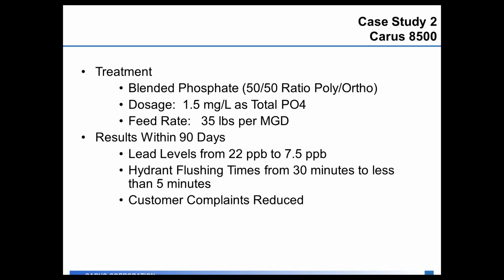Within 90 days of applying the blended phosphate to the distribution system, they had lead levels drop from 22 parts per billion down to 7.5 parts per billion. So now you're less than half of the action level of 15 parts per billion. Hydrant flushing times were reduced from 30 minutes to less than 5 minutes. So this reduced the amount of operator time in the distribution system to flush those pipes, plus the amount of wasted water. And then the customer complaints for red water in the system got reduced from several a month to almost none. So across the board, the blended phosphate helped them meet all the treatment goals that they had in the system.